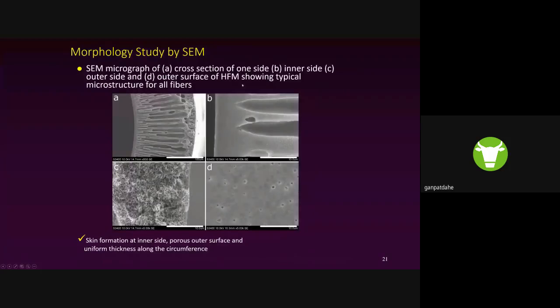If you look at this, this is the closer view of the hollow fiber. This is the inside of the hollow fiber. This is the outside of the hollow fiber. On the inside, you can see a very compact structure, and it's very difficult to see where the porous structure starts and the dense structure ends. For that reason we need a very high resolution image to know the thickness of the selective layer, and this selective layer is responsible for the separation.